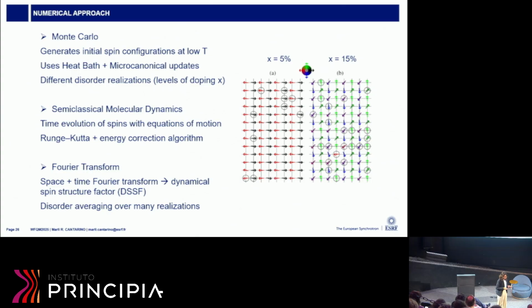And there is the semi-classical molecular dynamics, so the time evolution of spins with these equations of motion. At the end, we do a Fourier transform to get from this model the dynamical spin structure factor. This will be the structure factor that we compare with the experiments.